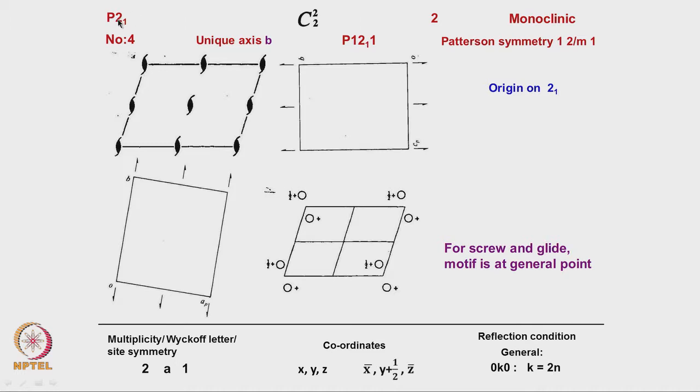The 2-1 corresponds to a two-fold screw. This is a short symbol, this is the correct symbol. This symbol is then primitive. Along the x axis there is a one-fold rotation, along the y axis there is a two-fold screw axis, then on the z axis there is a one-fold rotation, correct. Now you look at this, the symbol which is used for representing a screw is this symbol. This is for a two-fold screw axis.